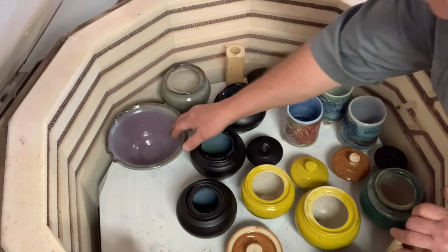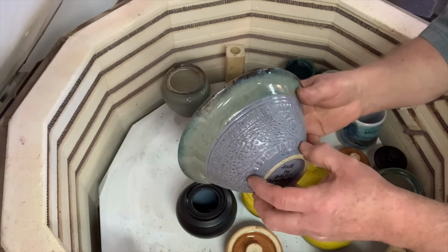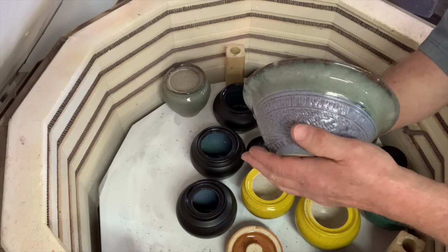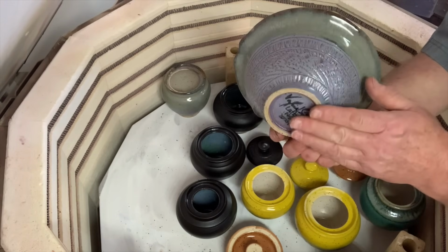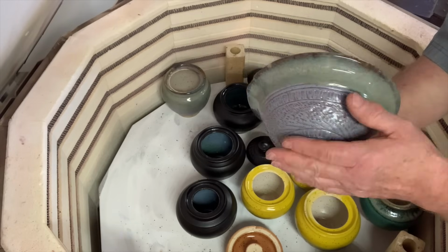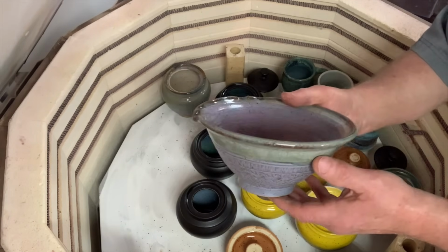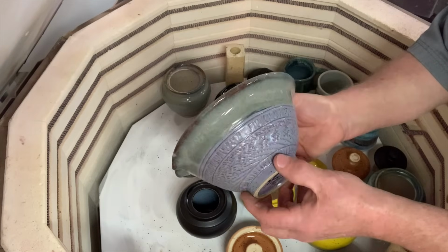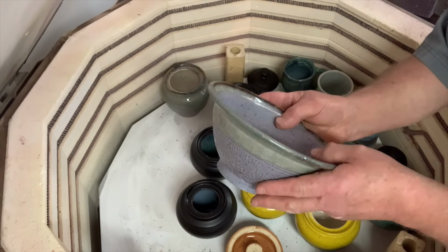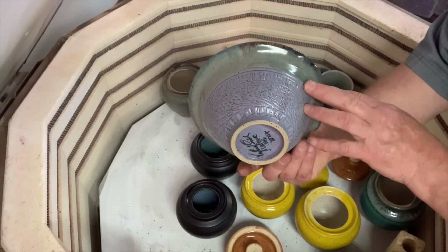The speckle clay I like to use for people who are microwaving a lot. The porcelain works in the microwave, but if you heat it up unevenly, like a piece of steak or fish that you're preheating in a microwave, it'll make the center of the plate get hot and the edges are still cold. And I've had pieces crack using the white smooth clays like a porcelain 5/16 white clay. It's a stoneware, but I have had a few pieces crack like that because of uneven heating in a microwave. This clay 455 does not do that.